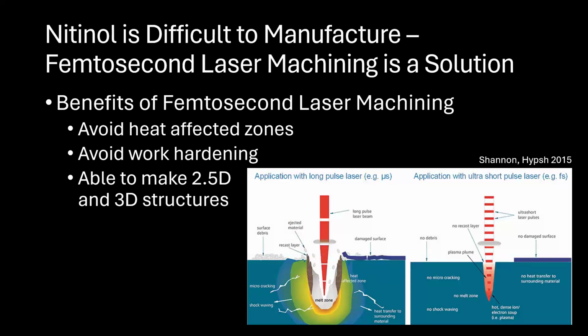However, nitinol is susceptible to heat-affected zones and work hardening, which degrade material properties, so many traditional machining techniques like long-pulse laser cutting and manual machining cannot be used. Nitinol can be processed using various techniques such as abrasive jet machining, focused ion beam milling, and photochemical etching, but these processing techniques typically cannot produce 2.5D and 3D structures.